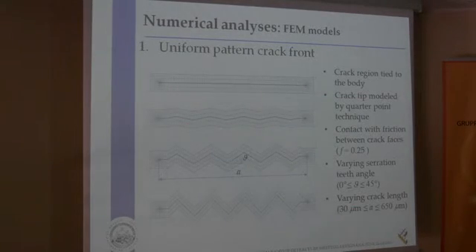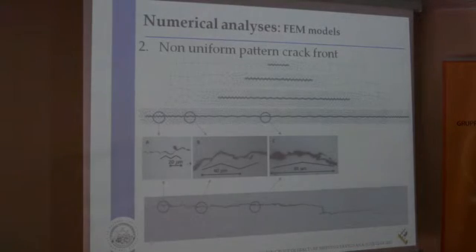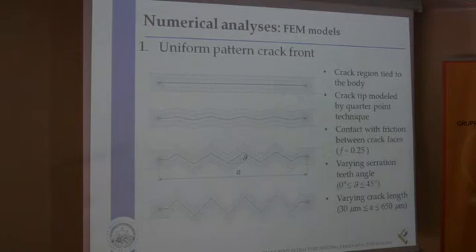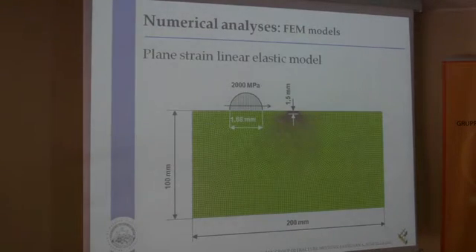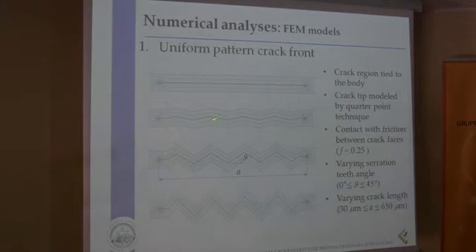Different finite element models were developed for the same. A first one is shown in this picture, a uniform pattern crack front model, which means that the crack is modeled with a faceted pattern with teeth having constant slope along the crack. The crack was modeled independently and then tied to the body with multi-point constraints condition.